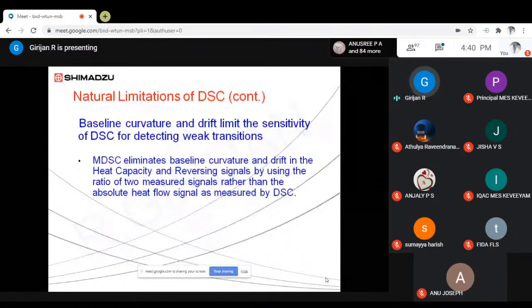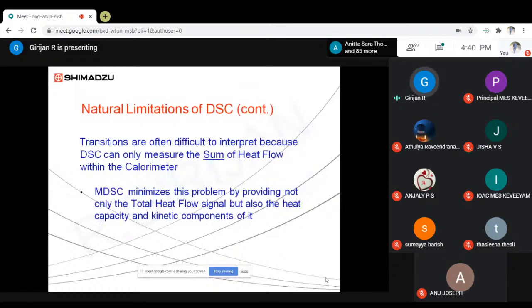Now, the second limitation of normal DSC: baseline curvature and drift limit the sensitivity of DSC for detecting some of the very weak transitions. For some of the weak transitions it may be difficult, because there can be some baseline deviations or drift, and that will limit the sensitivity of detection. But MDSC can overcome that. MDSC eliminates baseline curvature and drift in the heat capacity and reversing signals by using the ratio of two measured signals rather than the absolute heat flow measurement by a DSC. We'll understand when I come to the MDSC slide.